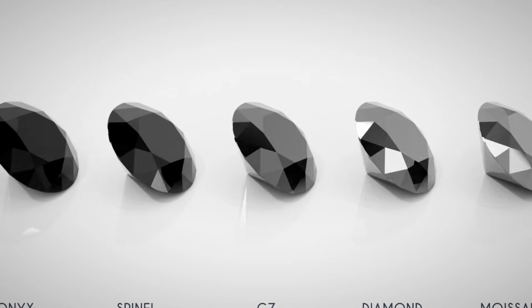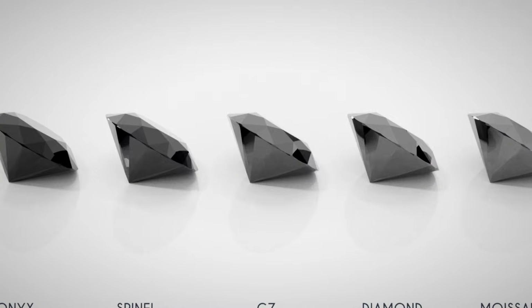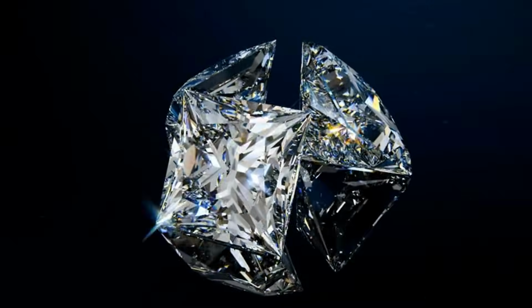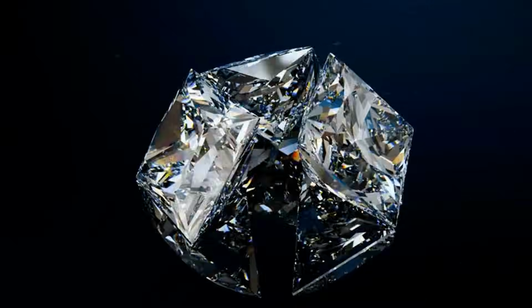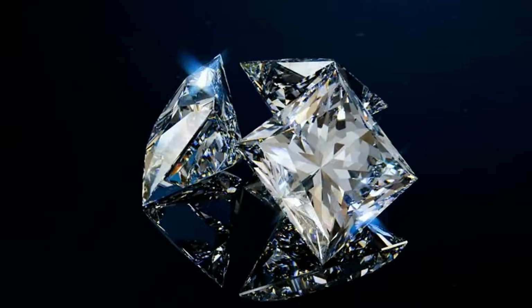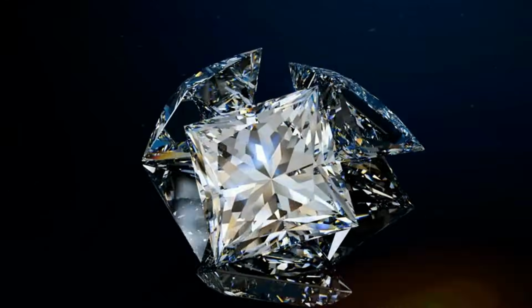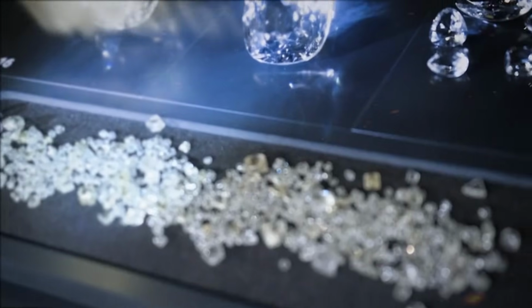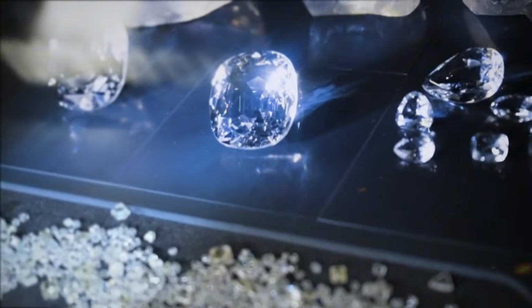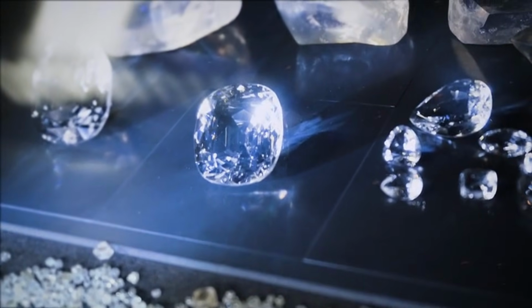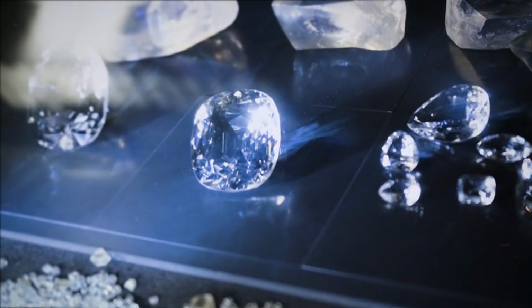Breathe directly onto the stone's flat surface, ideally the table facet, just as you would fog up a mirror. Then observe. A real diamond will dissipate that moisture almost instantly, within 1 to 2 seconds, due to its rapid heat dispersion. The surface will clear before you've finished blinking. By contrast, a fake stone, especially glass, cubic zirconia, or quartz, will hold that fog for several seconds longer, sometimes 5 to 7 seconds, due to their poor heat conductivity.